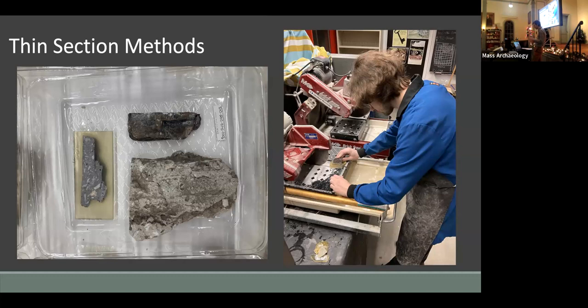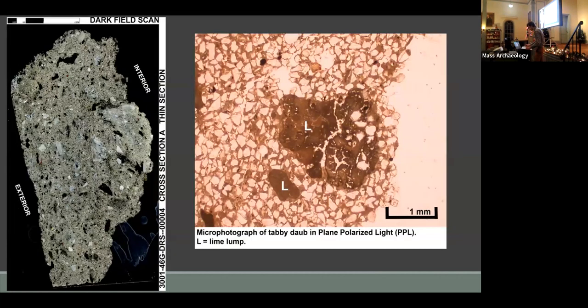These cross-sections were then scanned using a flatbed scanner as a means of photographing and documenting the cross-sections before further alteration. And from these observations made of the cross-sections, 14 samples were selected for thin section. In this photo on the left here, you can see a tabby fragment at different stages of the thin section process. So the large chunk at the bottom, that's the resin impregnated sample, so that can be used for further analysis. And then on the left here, you can see a tabby cross section that was then cut down more to size to fit onto a glass slide thin section. And so here's what the thin sections look like. Full characterization of these thin sections is still forthcoming. However, there are some interesting preliminary observations.